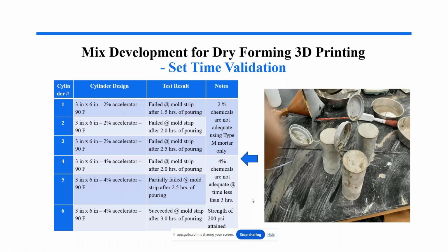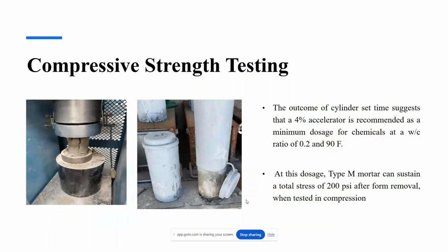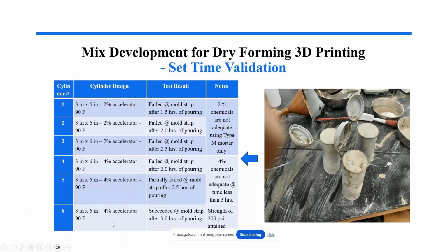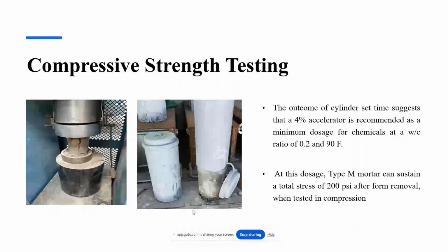given the productivity rate that the company was looking for. At this level, we kept repeating until we guaranteed that the injection at this water to cementitious material rate, and at 4% accelerator, could be used at a 3-hour time rate. Once we pour and inject our fluid, then in 3 hours we can start removing the printer, and we can generate a full-sized coral reef block.